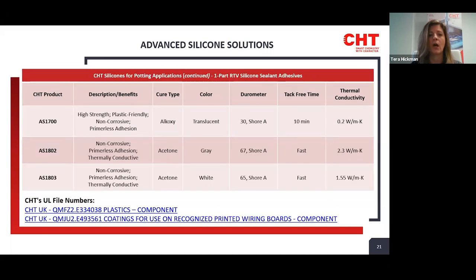Here are a few of our potting compounds to fill over the circuit board. These products are thermally conductive and will aid in pulling heat away from the board and components, making your product more efficient. The QCYL 553 has the highest thermal conductivity of these products — it is low viscosity, self-leveling, with good flow. Our other products are QCYL 550F, QCYL 550LV, which Michael used earlier, and QCYL 556. All are thermally conductive and UL rated. We also offer a customized white pigmented material, and for added adhesion we recommend QCYL Primer Number 3, which also comes in a UV tracer option for easy visual inspection under UV lighting. Additionally, here are one-part RTV silicone sealant adhesives for sealing leak paths — all are plastic and electronic safe, non-corrosive, and offer primerless adhesion. The AS1700 is a general purpose high strength alkoxy product, and the AS1802 and AS1803 are thermally conductive materials used to bond boards and attach heat sinks.